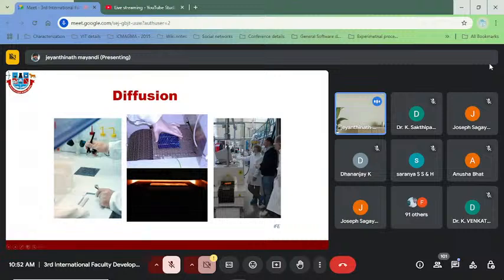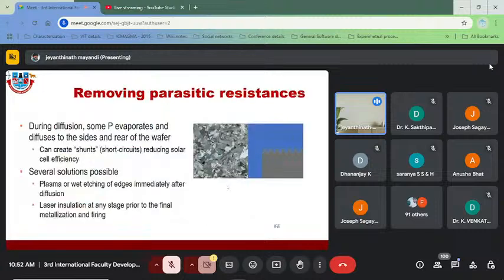The other one is where you can spray. This is another technique where you spray, and then put the wafers into a belt furnace with different temperature zones. So this is another way of doing phosphorus diffusion. Once the diffusion is made, the phosphorus is diffused on both sides, also at the rear. So to avoid shunt resistance, you need to cut out the edges of your solar cells, or you can etch them with plasma after diffusion. This is very essential to remove the parasitic resistance.